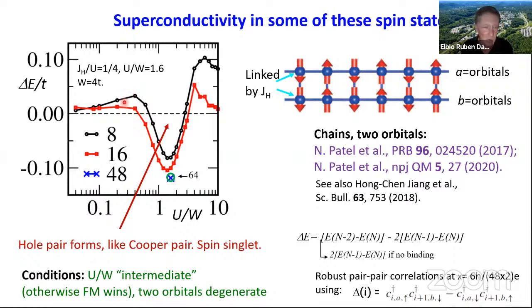You don't get a perfect zero, but you see as you go to size 16, it is going down. Here it is also going down. The good thing is that there is a negative region. The negative region indicates that there is a bound state. This is like a Cooper pair, essentially. And this is very costly numerically. So we only have, at the point that was supposed to be the best for the pairing, 48 sites and 64 sites. Fortunately, they lie one on top of the other. I think it is confirmed that you have a tendency to form a bound state. So this is like a Cooper pair. It's a spin singlet.